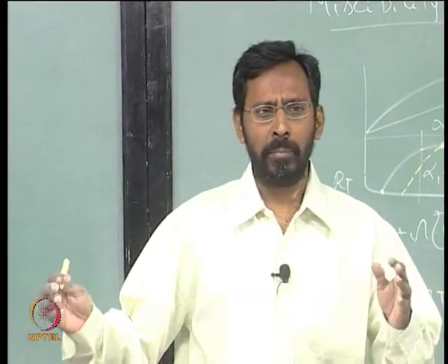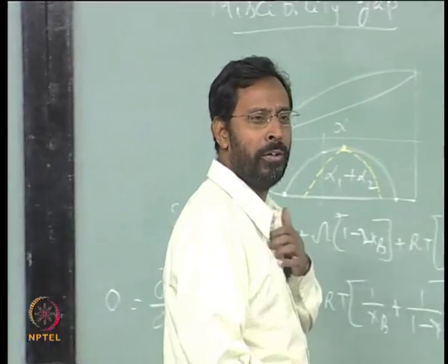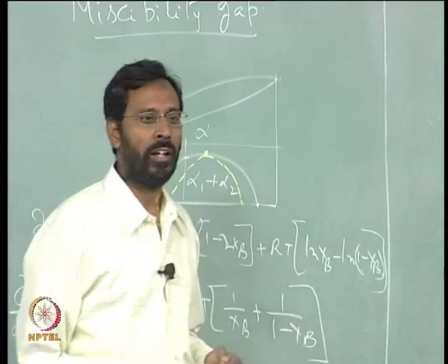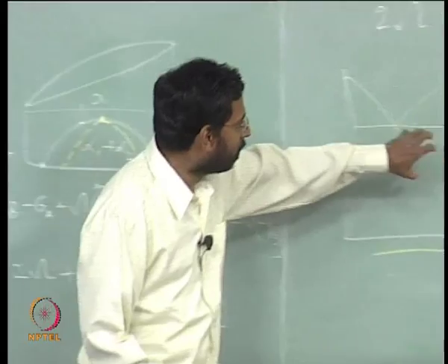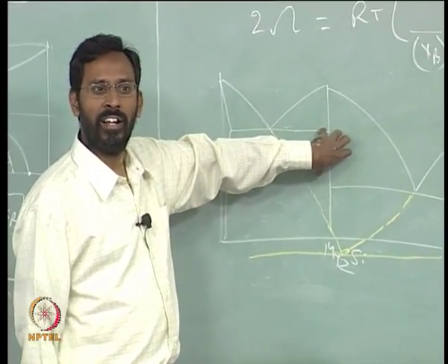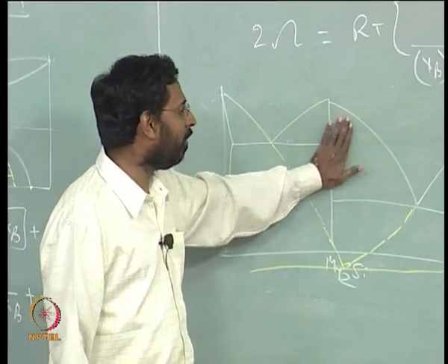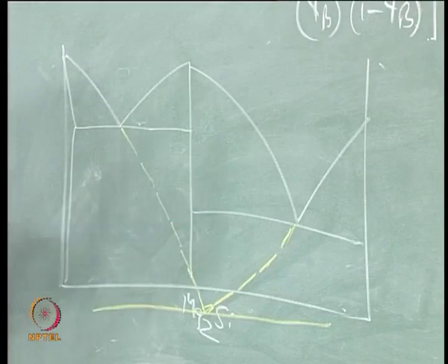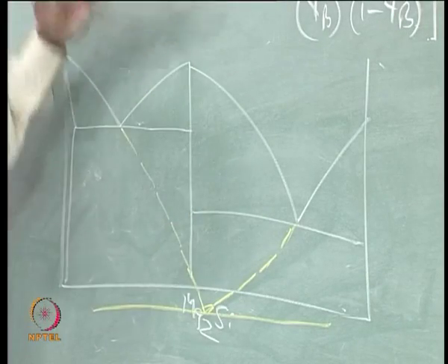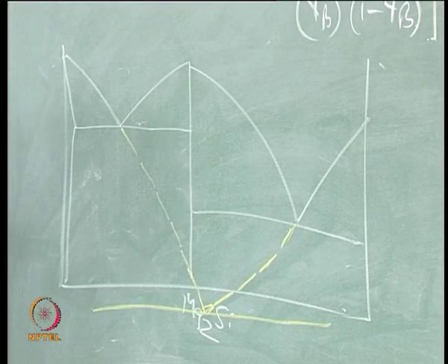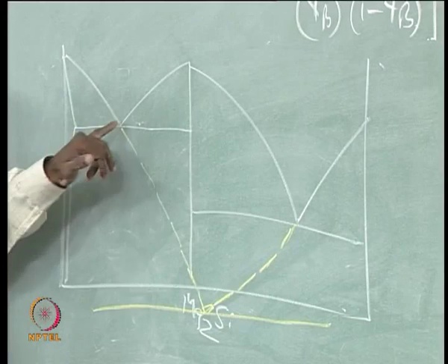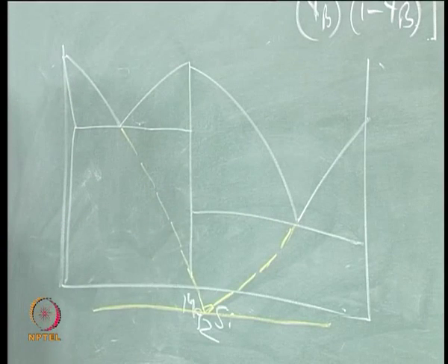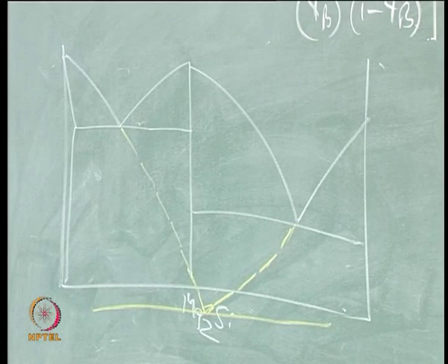So in a phase diagram, if there is a normal eutectic like iron boron, I can say yes, that is a composition where you can get a glass. But if you see things like this, if you start thinking that this is not forming, what is then going to form? That liquid at that particular composition is going to be undercooled continuously, until you reach this temperature. And so that means in this alloy, though the two eutectics are shallow eutectics, still this particular phase diagram can give you a glass.